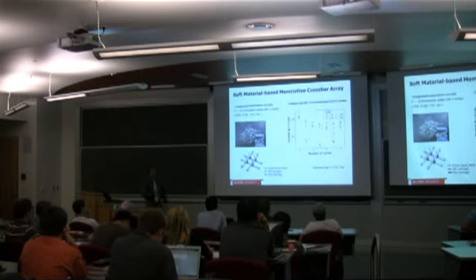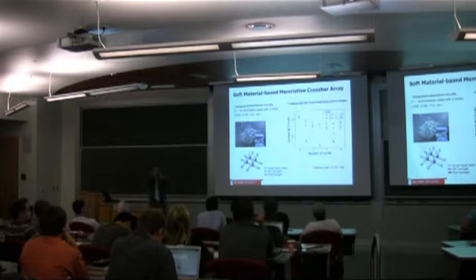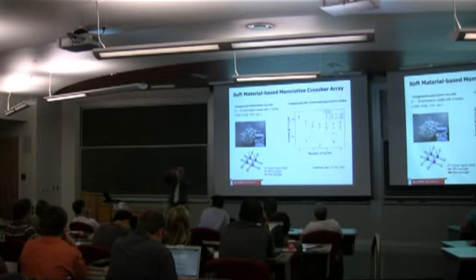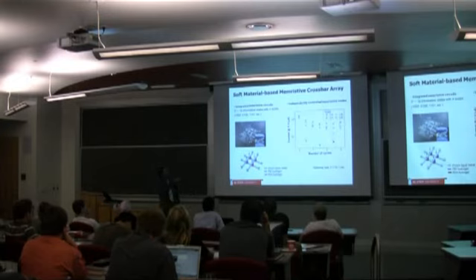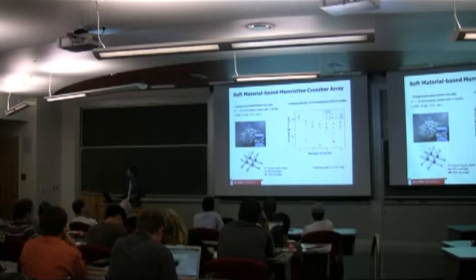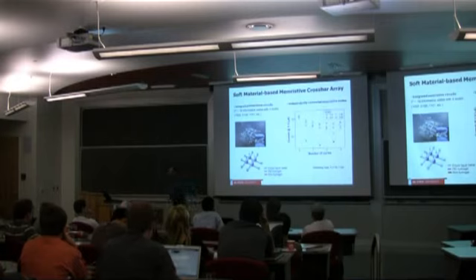And so we took this kind of to the next intuitive step, which was to make multiple junctions. So we made a 2x2 crossbar. So imagine 2 wires and 2 wires crossed like this. At their junction, we put the gels, and we showed that we can start with all of them turned on. We can turn one off while leaving the others on, turn it back on, and take another one, turn it off, turn it back on. So this just shows you can independently address each node. And again, I emphasize Hewlett-Packard is not shaking in the boots at this work, but it's made out of Jello, which I think is,